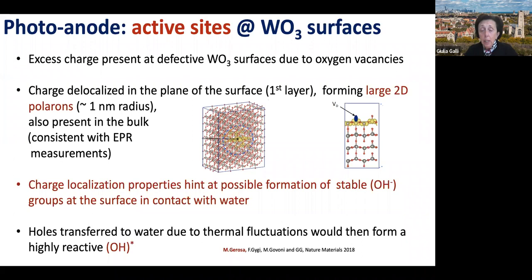When we saw this, of course, we were worried that this was an artifact of our calculation. We kept trying larger cells, but we also went to the bulk and asked the question, is there really a large polaron also in the bulk? And we did calculations with 1,000 atoms. And indeed, we also found a large polaron in the bulk. And this is consistent with EPR measurements.